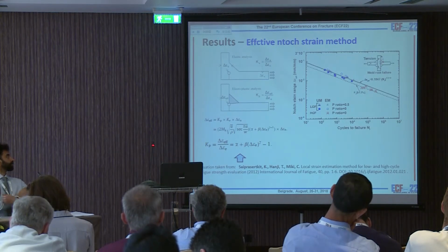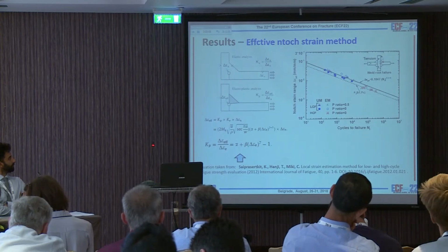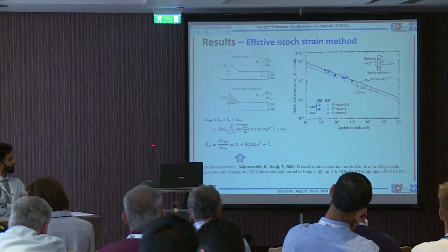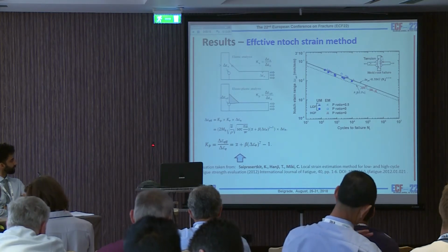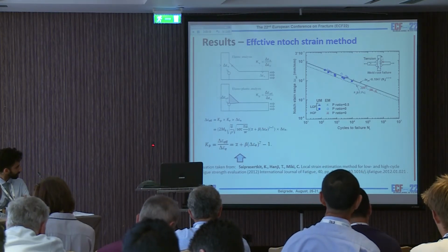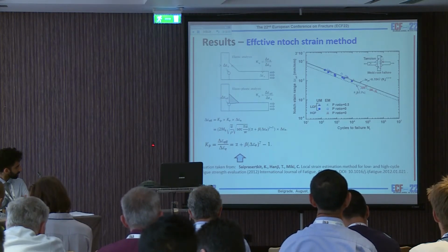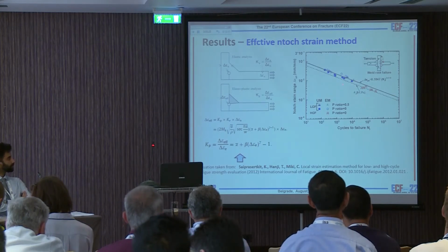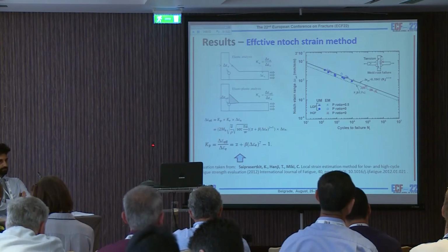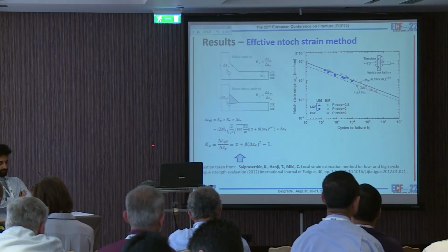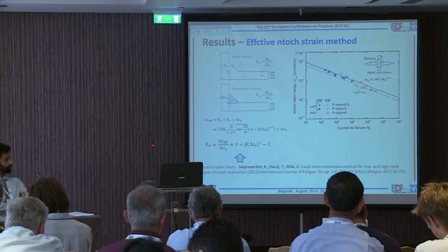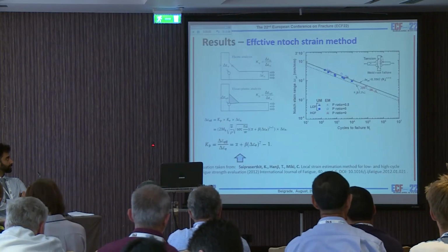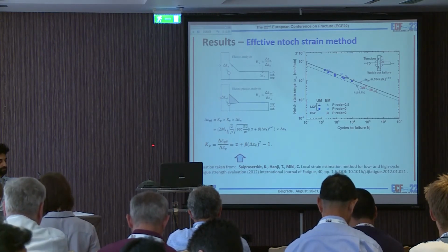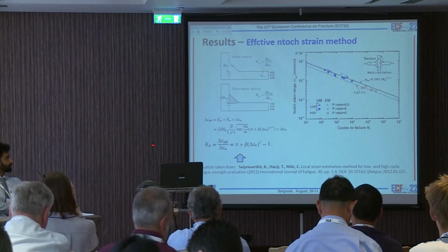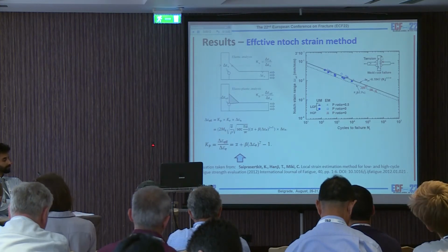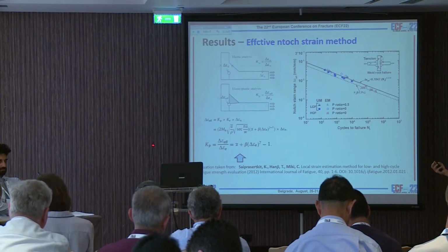And then additionally, I used the effective notch strain method to evaluate this data in the diagram, and this analytical solution is from a Japanese researcher, and he gives some solution for the welded root prediction, and he also used this analytical solution to predict the welded toe failure as the engineering estimation. But for the low cycle, for this load carrying cruciform joint, we could not find a solution to estimate the value between the welded root and the welded toe.